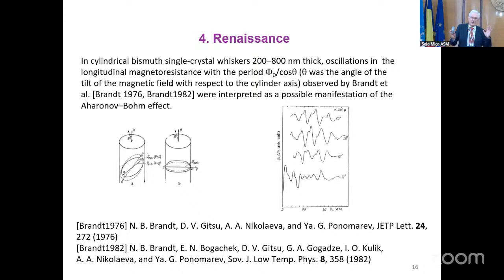Cylinders are something which is singly connected, but in those whiskers, the currents were developing only, I would say, in the skin layer at the surface. So the area where the currents were flowing was doubly connected like rings. And they observed oscillations. Please look at the second panel here. Depending on the tilting angle between the magnetic field applied and the axis of the whisker, because the area of the loop was changing, the period of this transport phenomenon was just representing this change of area.